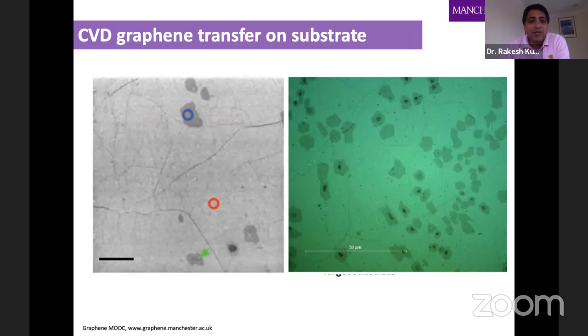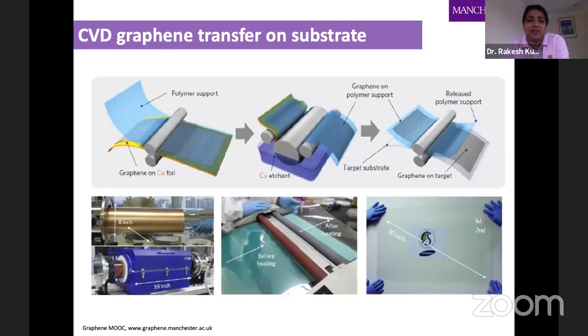8-inch wafer. So this is what you see, an optical image of graphene on a silicon oxide surface. The picture on the left is monochrome, and the one on the right side is a color image. And you can see those patches and impurities trapped under the graphene film. And there's another method of graphene transfer called roll-to-roll transfer. Just like roll-to-roll synthesis, there's another way of roll-to-roll transfer. And this is very special and useful for transferring graphene onto flexible electrodes for wearable and flexible electronics or sensor fabrication methods.